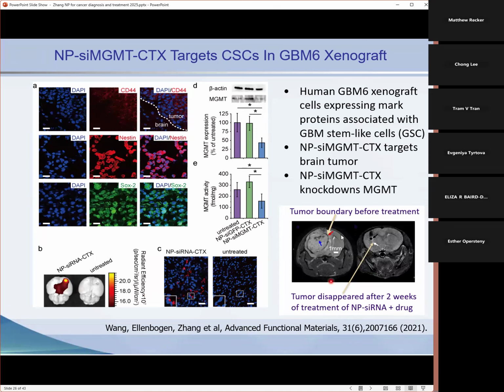And then I also want to show this MRI imaging. This is a tumor, and this is after injection. Initially we see the big tumor with black boundaries, and after 2 weeks of injection of nanoparticle siRNA plus the temozolomide, the tumors disappeared. So this is, of course, not always the case. If it were always the case, we would have a very good particle for treatment that should go to the clinic right away, right? But we've seen quite a few mice like this. So it's really